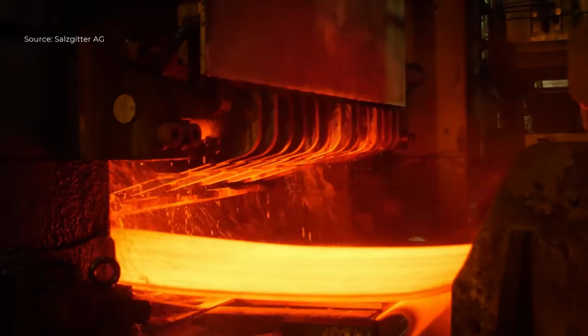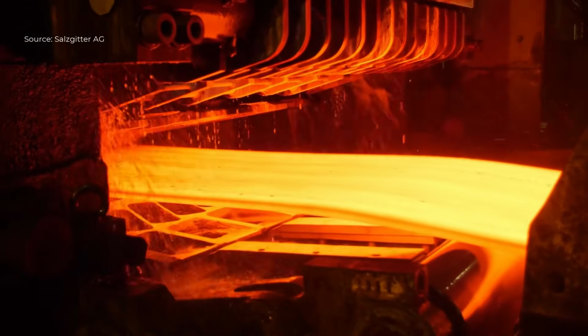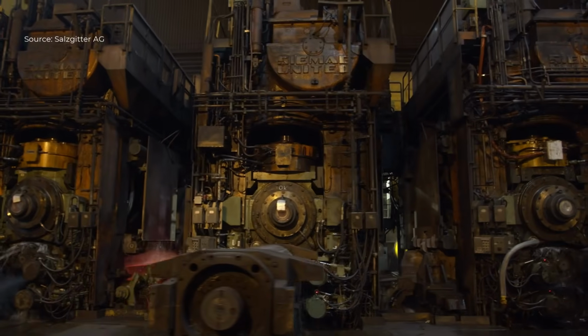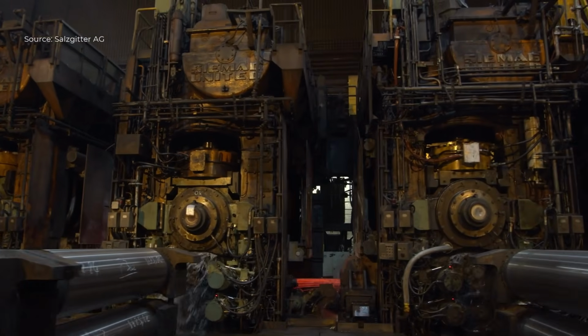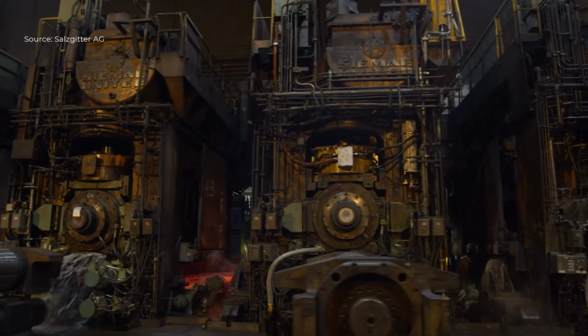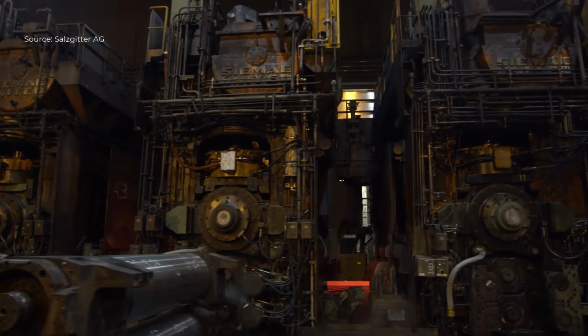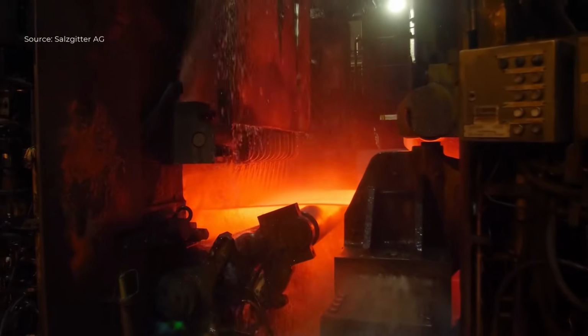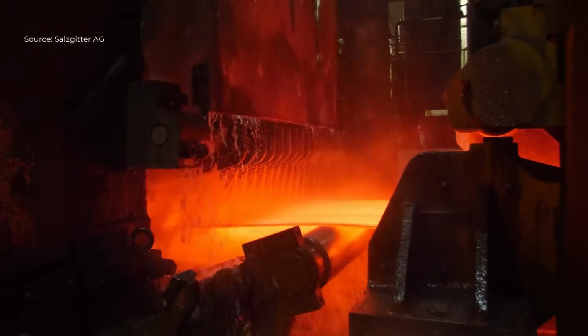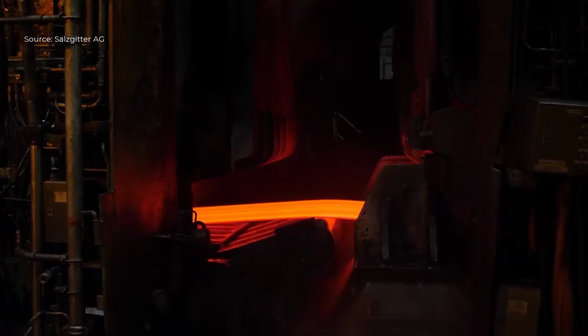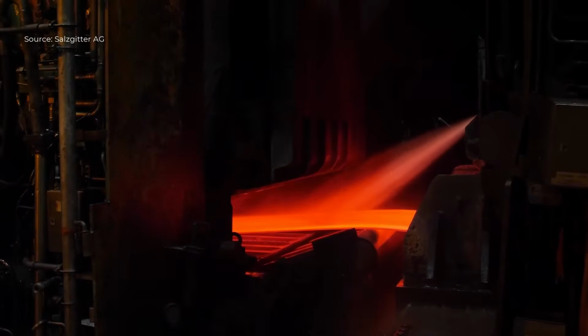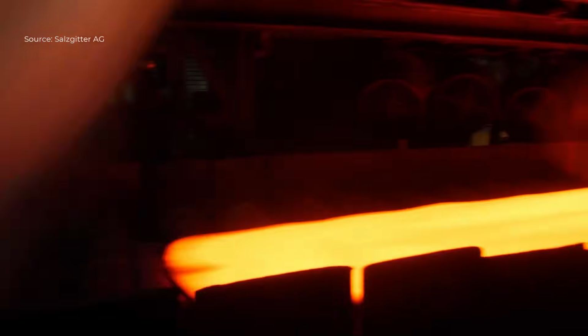After roughing, the steel strip moves directly into the finishing mill, Fertigstrasse. Each stand is powered by drives rated at 30 megawatts, around 40,000 horsepower. Here, the strip undergoes precise thickness control and is rolled down to its final gauge, ranging from 25 millimeters to as thin as 1.5 millimeters, with widths reaching 2.020 millimeter. At this stage, the strip can already be hundreds of meters long.